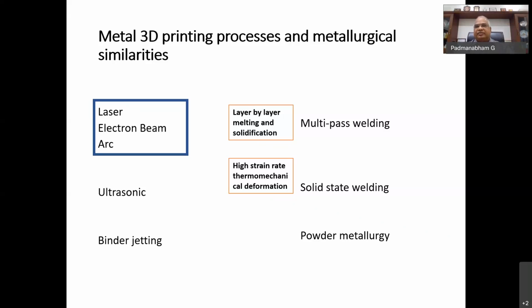So a lot of our knowledge from these fields can be brought into additive manufacturing to successfully understand it and then implement it for our applications. So those of you who are familiar with welding, the moment we talk of multi-pass welding, we talk of what kind of interface we are forming: fusion defects can be there, cracks can be there, porosity can be there, inclusions can be there. All these issues we are aware of, and similar things are possible in the layer by layer building of components in melting and solidification. In fact, when you talk of multi-pass welding, in a 10 mm thick plate at most you will complete in about 3 to 4 or 5 passes. But in this layer by layer deposition, you have multiple passes for one layer itself, and layer by layer, it runs into hundreds of thousands of passes.